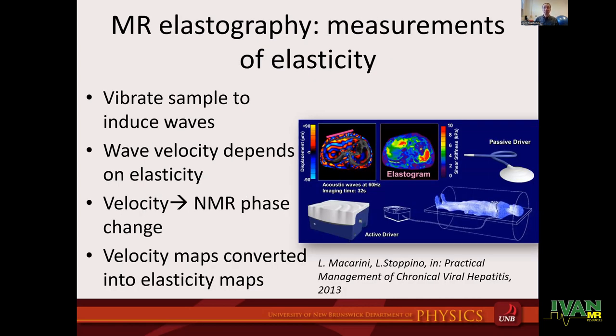When it comes to elastometry, we have a very well-developed field called MR elastography. So you vibrate your sample to induce waves. Those waves propagate, and the wave velocity depends on the elasticity of the material. And you have the NMR phase change. You measure the velocity map. You convert it into an elasticity map. That's pretty much how it is done.